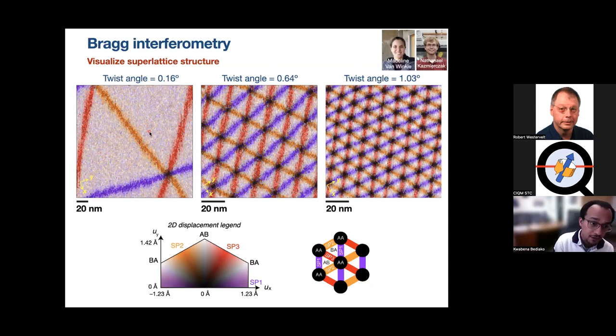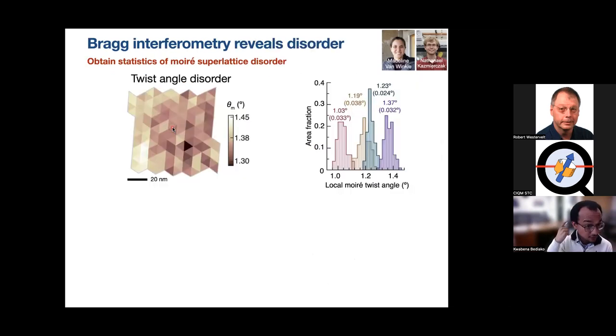And so here is a sampling of a data set going from 0.16 degrees all the way up to 1.03, and we go further than that. Okay, and so you can see these different boundaries now between the various stackings, once again emphasizing the point that we have some sort of relaxation process going on, as we suspected from the previous experiments. But the nice thing about this technique is that for even relatively large twist angles, we can map these Moiré superlattices over a fairly reasonable area.